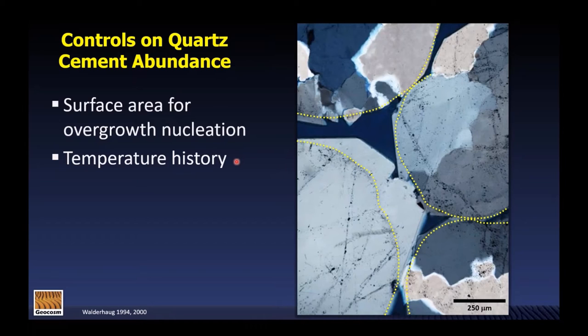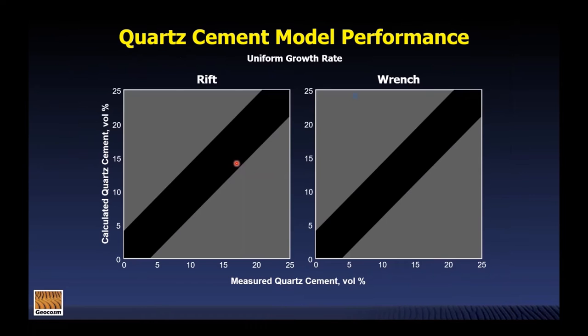Now the other factor here is the temperature history, and what we've found is that we can use our old friend the Arrhenius equation to quite nicely depict the temperature dependence in the rate of crystal growth in quartz. So with this in mind, let's take a look at the performance of this type of modeling approach on two very carefully collected data sets.